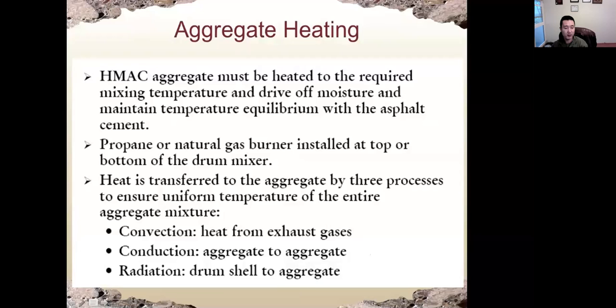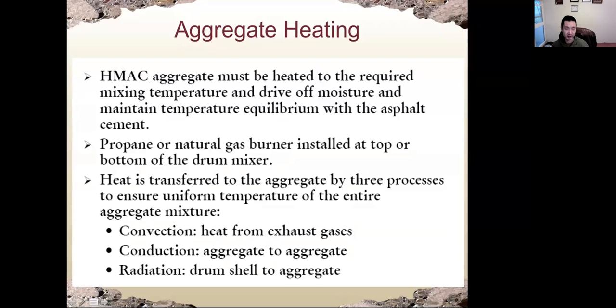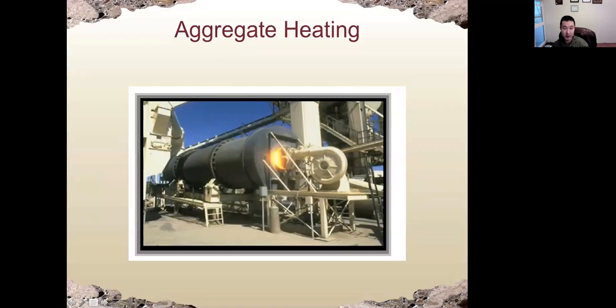Okay. So aggregate must be heated to the required mixing temperature. Two purposes. One is to drive off the moisture, and the second one is to maintain the same temperature as asphalt cement, so we can mix asphalt binder with the aggregate. Okay. And here shows us what heating methods could be used for the asphalt aggregate. Here is a picture of aggregate heating. This is the aggregate conveyor, and we have a dust collector, and the aggregate is heated up in this big oven.